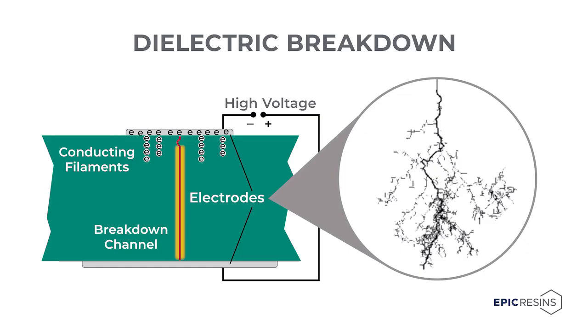This is an illustration of dielectric breakdown. As a voltage is applied, electrons build up on the surface of the electrode. If there is a path of unstable electrons, the charge will travel through the polymer as shown. The more stable the electrons are, the more difficult it is to make them move through the material. We formulate polyurethanes that have molecular structures, fillers, and additives with very stable electron shells. When formulated this way, it significantly impedes the flow of electrons and increases dielectric strength.